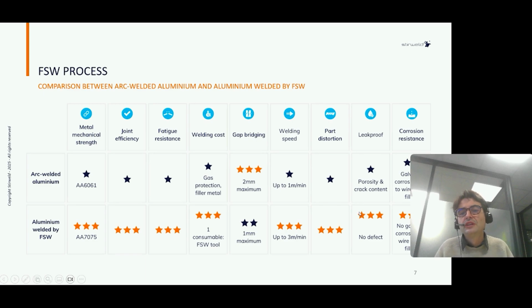Now, if we look at welding speed, maximum for arc welding and MIG welding is 1 meter per minute, while we can reach 3 meters per minute by friction stir welding. Part distortion is like joint efficiency. As you know, the main problem of welding generally is part distortion. But as the process temperature is 2 times lower with friction stir welding, the part distortion generally is 3 times lower. Not 2, but 3 times lower.